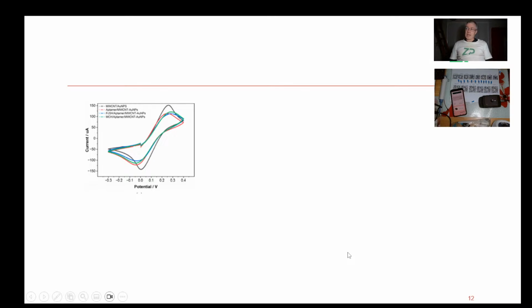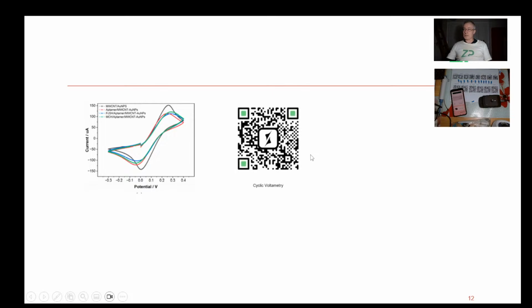Now, in this particular paper, this is kind of classically done, that they're following their functionalization using cyclic voltammetry. So they build up layers. In fact, if anything, the electrode gets more sensitive as they put their multi-wall carbon nanotubes and their gold nanoparticles onto the electrode. And then as they build up the biological layers, the cyclic voltammetry gets a little bit more distorted, and that's expected because essentially these macromolecules, as they start to coat the surface, are starting to block that surface. Not terribly, but they are doing it.